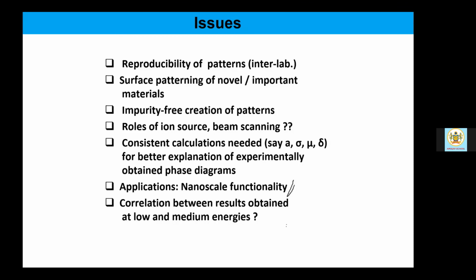And uniformity also is an issue, of course, because those are millimeter size or centimeter size beams. But with the broad beam ion sources which are used for low energy ion patterning, a big uniform beam up to 2 inch or so can be easily achieved. 1 inch to 2 inch can be easily achieved. So basically wafer scale integration is directly possible. And over and above, if we can scan the beam to a 4-inch wafer, it's even a win-win situation for the industry. And then consistent calculations are needed for those energy ellipsoid, we have already said.